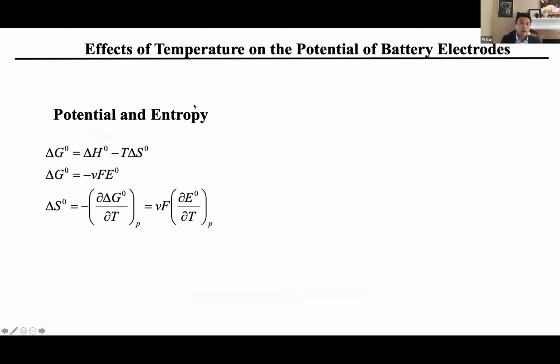I also want to emphasize that temperature affects the thermodynamics of the battery electrode, particularly the potential. The potential, also the voltage, is related to delta G of the reaction, right? How delta G translates into voltage is through the Nernst equation. That's the origin of the voltage of electrochemical cells. The voltage temperature coefficient is related to delta S, the entropy of the system. In the electrochemical system, this delta S turns out to be quite big because of the solvation energy, the solvation entropy of the lithium ion or other ions, if you look at other systems. The solid state can also provide the mobile ion quite a bit of entropy contribution.